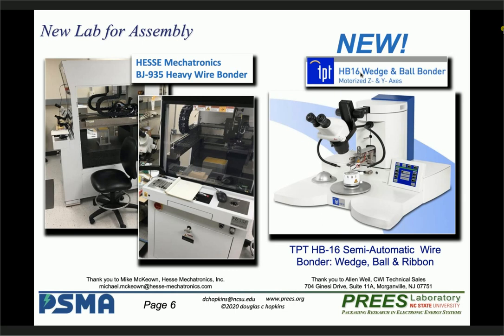We also have a new capability in the lab, which is now a small wire bonder. HESSE has been providing us with the heavy wire bonder for years. This gives us down to 4 mil wire capability, but now with the TPT system, it goes from 4 down to sub 1 mil wire. And we need this now because on the smaller wide bandgap devices, the gate regions are becoming smaller. It's very typical in many of the big modules with IGBTs, et cetera, that you might use one size wire for the power die, but smaller wire for your gate structures. This gives us the capability to start mixing different, smaller wire sizes.